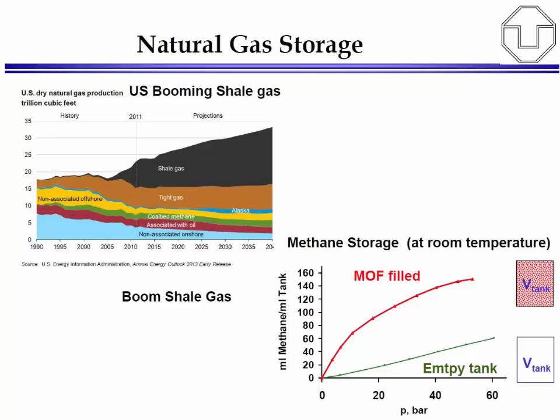So metal organic frameworks can store natural gas at room temperature. So you can see on the right bottom basically the advantage of a MOF-filled cylinder as compared to an empty tank system. You can increase the storage capacity by a factor of 2 to 3 as compared to the empty tank system. And the reason that you can achieve a higher storage capacity is that basically the MOF assumes a higher density in the pores. It's a liquid-like state, essentially, so a higher density, and this is the reason why you can achieve a higher packing density of the gas and a higher capacity.